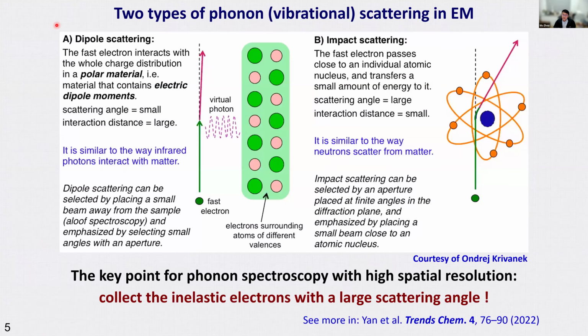To start with, we just very briefly introduce how we can do that. Measuring the vibrational signals in the electron microscope, we can collect the signal through two different mechanisms. One through the dipole scattering. This is mostly done on polar materials where the electrons will excite the phonon, and we collect it with very small angle, and those signals would be very strong, but their interaction distance is very large, so